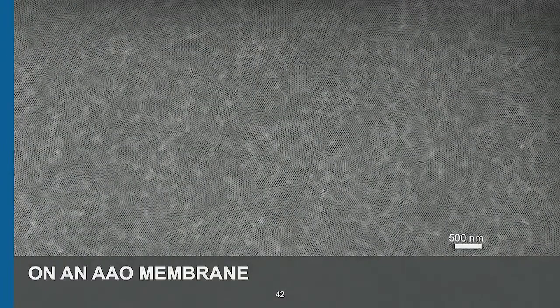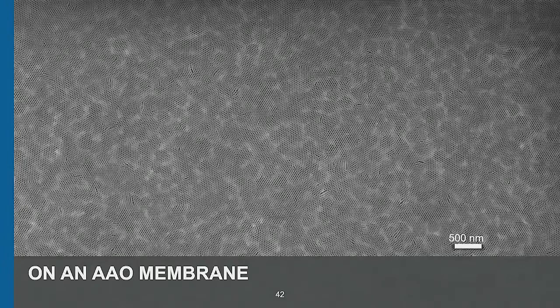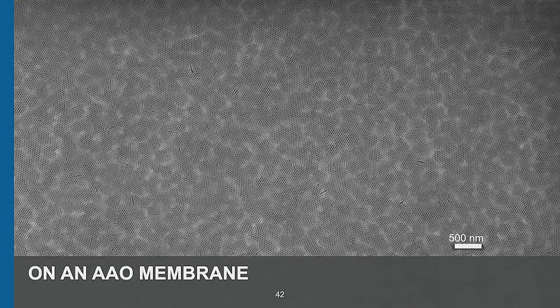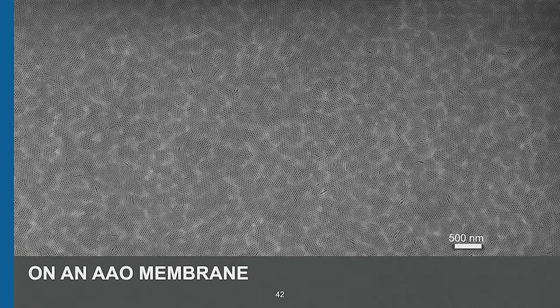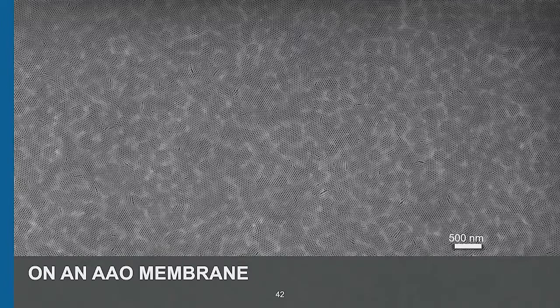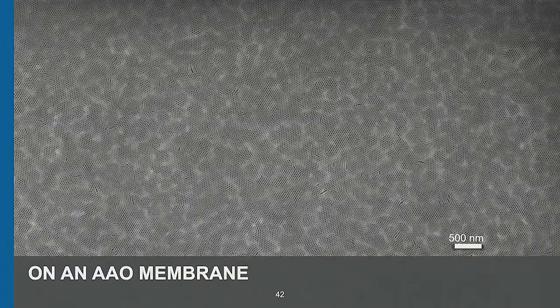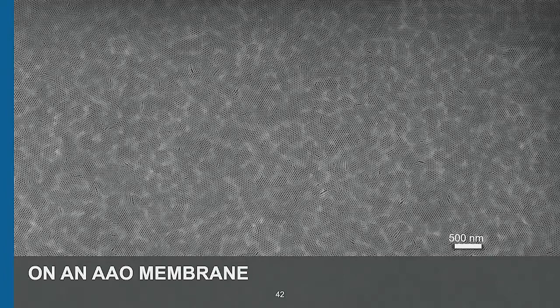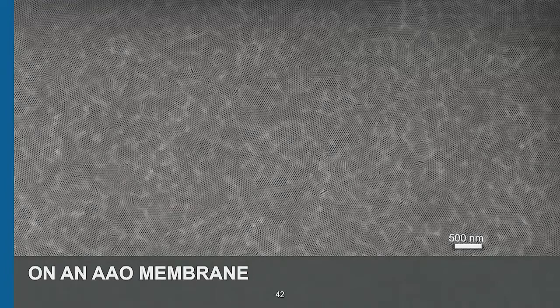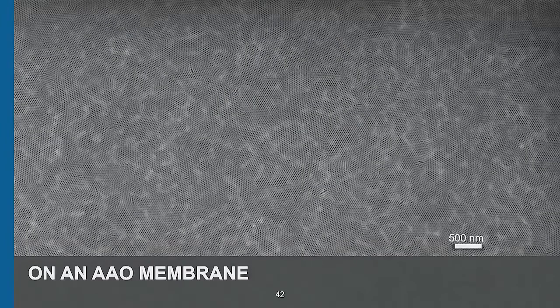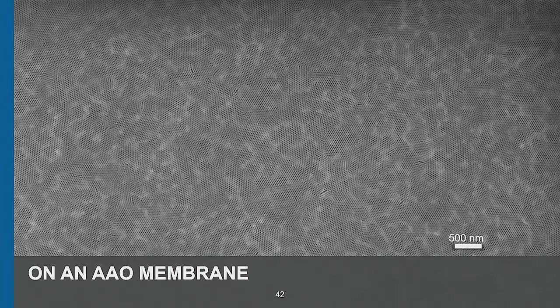And if you doubt if these things can actually be made at scale and put onto another membrane, if I zoom out further, you can't see the pores anymore. But this is one of those meshes, so only about a 30 nanometer thick block copolymer derived membrane placed on top of, in this case, an anodic aluminum oxide membrane. So these dark circles you see are the underneath pores of the macropore support, and on top of it is this oxide membrane, and we can cover, you know, square inches with this thing.